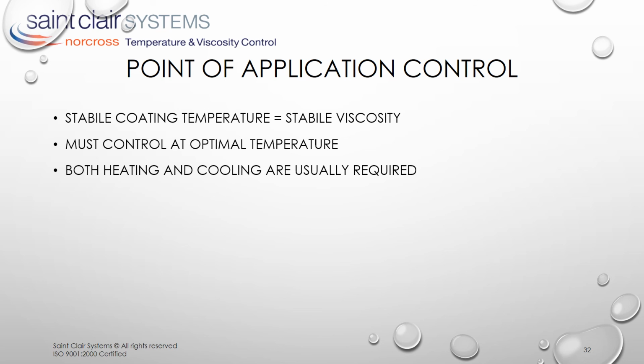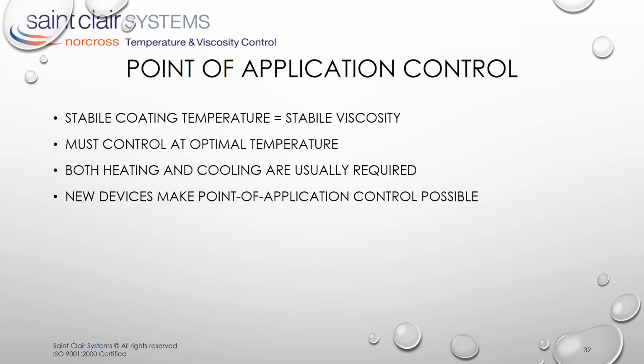We have also demonstrated that many systems generate friction as a part of the delivery and application process. This friction manifests itself as heat, which must be removed by the temperature control system. In virtually all modern coating applications, a system capable of both heating and cooling, and of switching seamlessly between the two as required without operator intervention, is essential. Recent advances in both methodology and thermal transfer devices make temperature a tool that can be utilized to protect the integrity of virtually every coating and optimize the performance of both the coating and the application process. These move temperature control from the bulk supply at the beginning of the process to the point of application, where it can have a more positive impact on the overall performance of the coating process. This adds another important parameter to the list of those that combine to control the process.